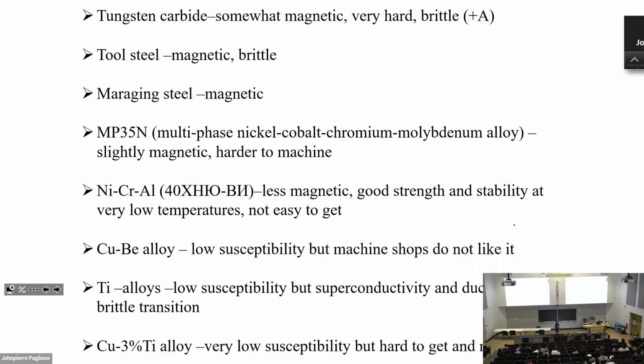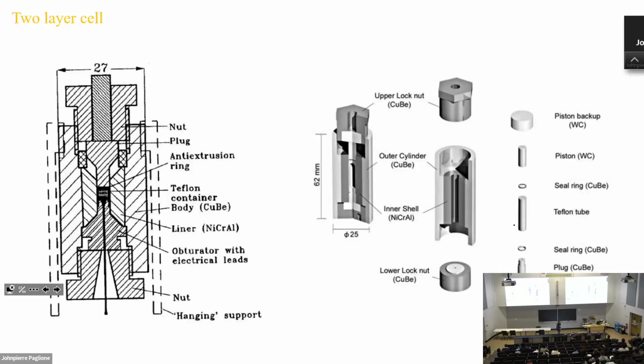In the literature, you will see a lot of cells that are a combination of many of these materials. That's because now people typically use two layers of cell. One layer is for one purpose, the other layer is for another purpose. For example, in this design, from the Japanese paper, actually later on, I think they started a company. The inner cell uses nickel chromium aluminum. The strength is not as good as beryllium copper, at least at higher temperature. So they have another layer of cell with beryllium copper.